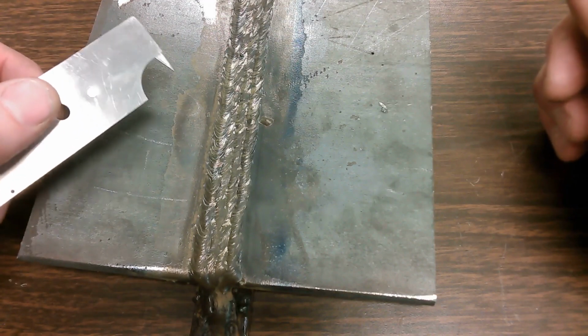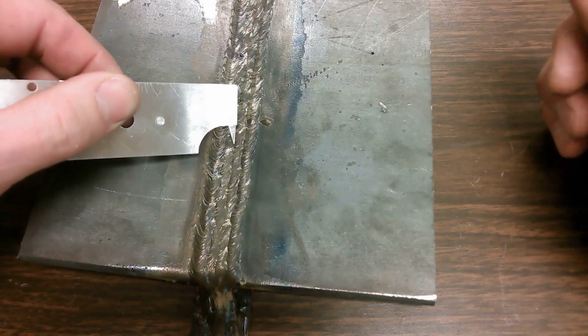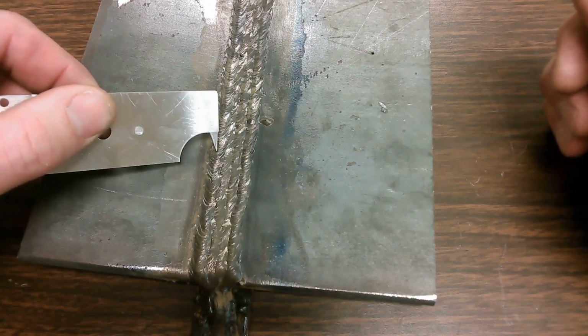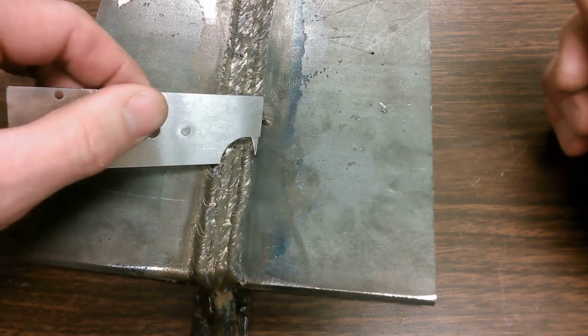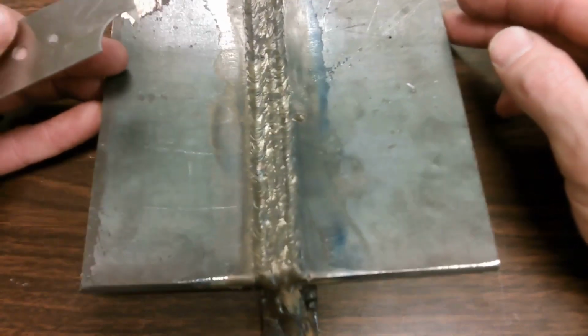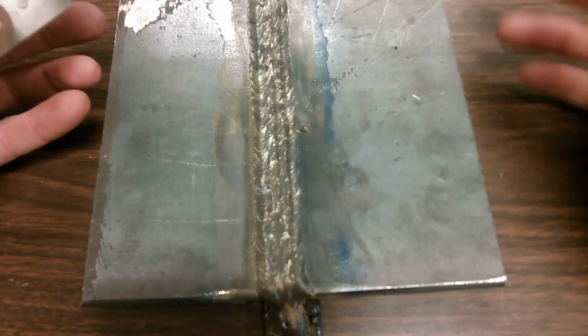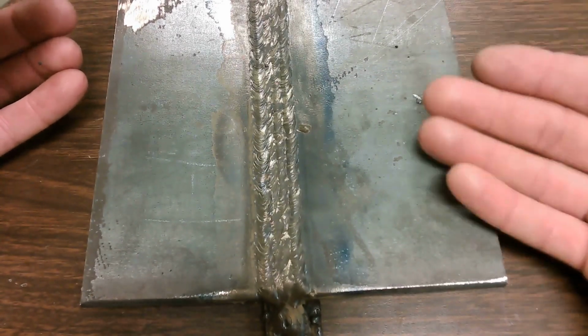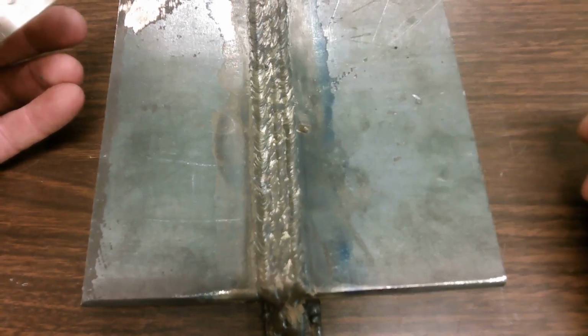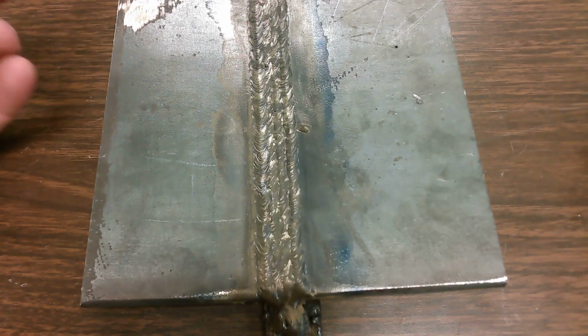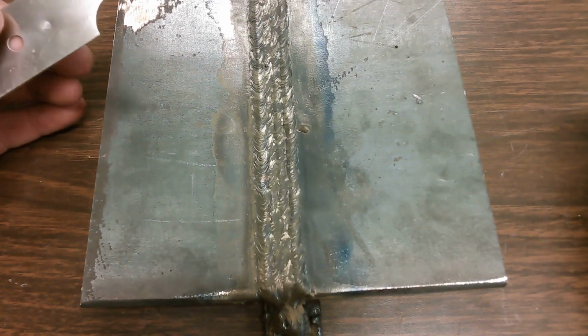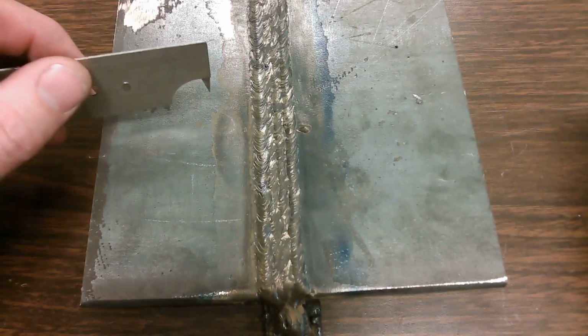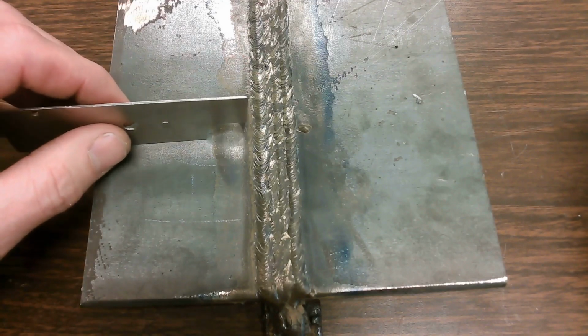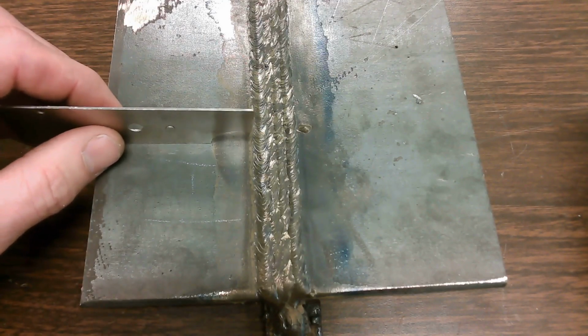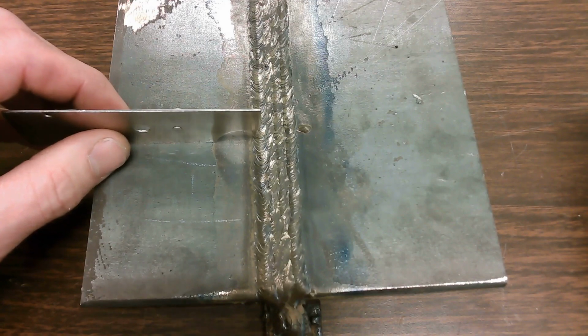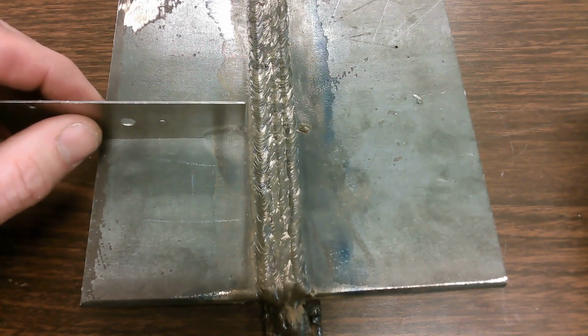One area that I noticed though, looking right down the middle of this, it does look a little bit recessed from these two beads here. And I want to check that for potential underfill. Underfill is where the bead just didn't quite come up to the surface of the base metal, and that's not a complete joint at that point. It would not meet criteria. So even though they don't specify underfills in the criteria, the joint does need to be complete. So that is a big one.